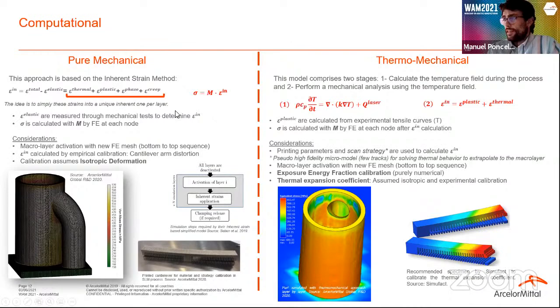This is the first model, and then the second model is a thermomechanical model, which is a little bit more sophisticated. It calculates initially the temperature field, and after calculating the temperature field of the macro layer, it runs the mechanical calculations. So in this case, what we have to feed to the software is the elastic and plastic behavior of the material at different temperatures. We do that with experimental tensile curves. And in this case, we don't need to calibrate the inherent stresses. They are calculated in the software from the input printing parameters and the scan strategy.